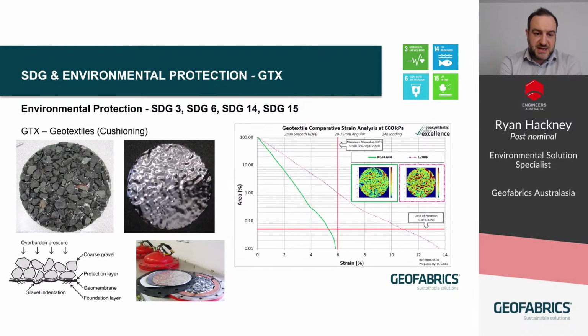If we focus on cushioning, in terms of protecting that geomembrane that's used for containment, we use what's called a cushion geotextile. And this is a heavier grade geotextile, typically a heavy grade staple fiber. And this sits within the system, typically next to the geomembrane liner, and it cushions the effect of a drainage aggregate or an aggregate material that can impose stresses onto the underlying geomembrane.